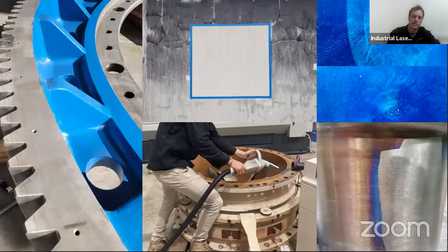The central one there, you can see fire damage remediation. You can probably do with a 200 watt laser 4 to 5 square meters an hour. With a 500 watt laser, you could do 10 to 12 square meters. The top right, we've got improved NDT dye penetrant results after the laser passed over the surface. Bottom right is cleaning the heat affected zone on some stainless after welding. And then middle is an IGV inlet for a gas turbine, I believe. That's that.